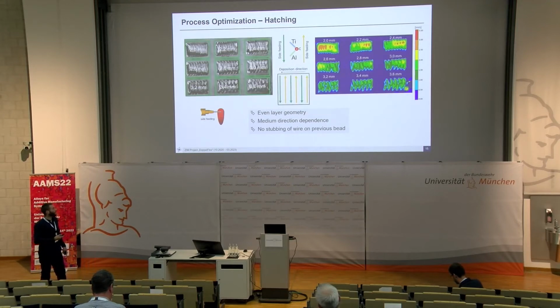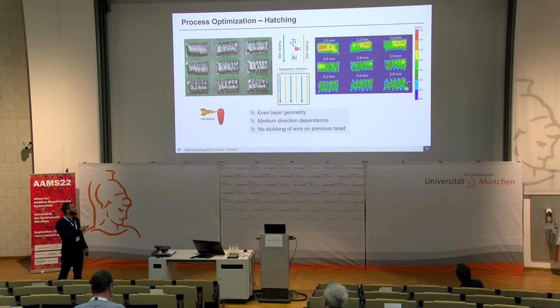So we did another hatching, with a complete side feeding. And here we see a lot more even layer geometry. We have a medium direction dependence, and we have no stubbing of the wire.